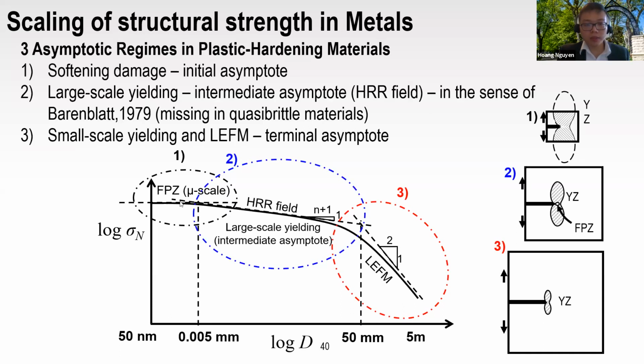And here we hypothesized three types of asymptotic domains. The first one would be the FPZ scale, which is the micron scale. The heterogeneity size of the metal is quite different from the concrete or other quasibrittle materials, in that it depends on the grain scales or the grain boundaries, where grains with different crystalline orientations are arranged differently and separated by the boundaries. Also, you have the rise of the intermediate regime when you have the large scale yielding. And when the specimen becomes bigger and bigger, this yielding zone will be very small compared with the entire structural size, and then it converges to the LEFM theory.